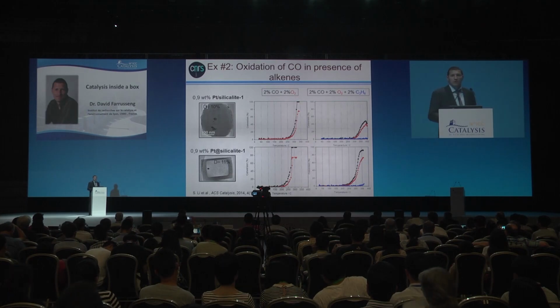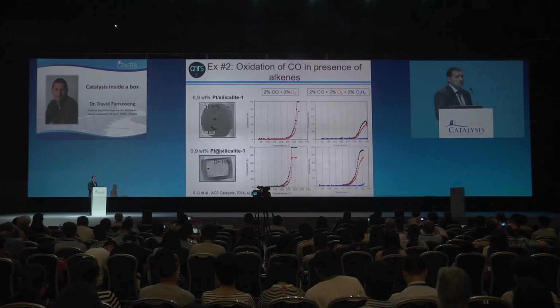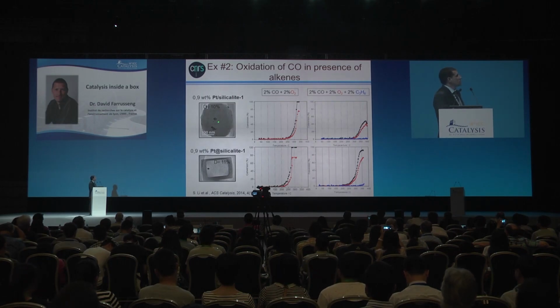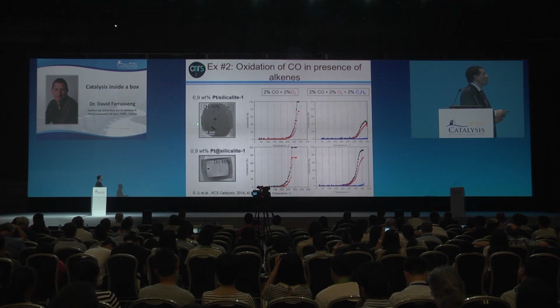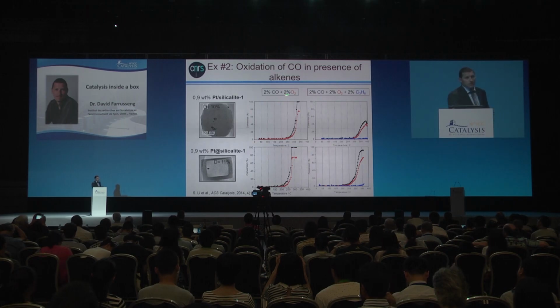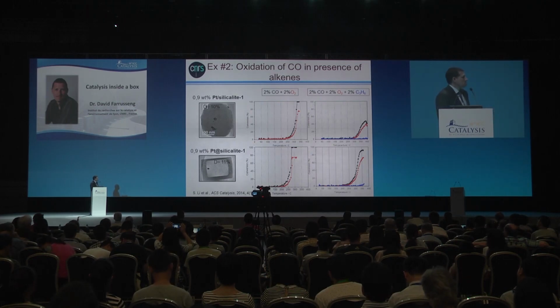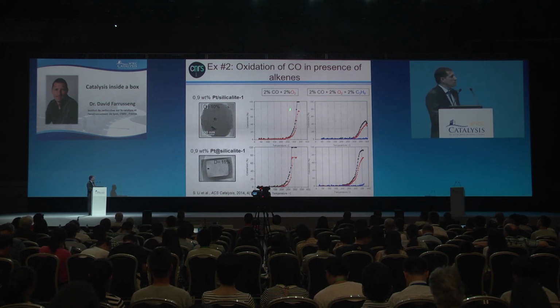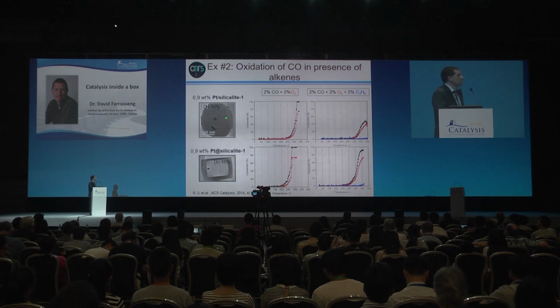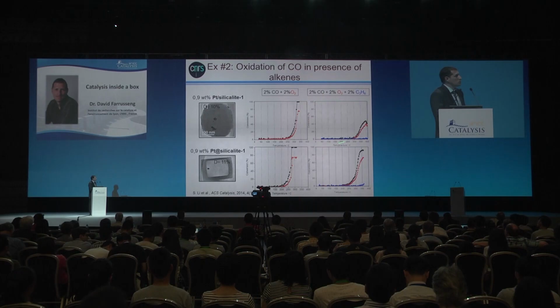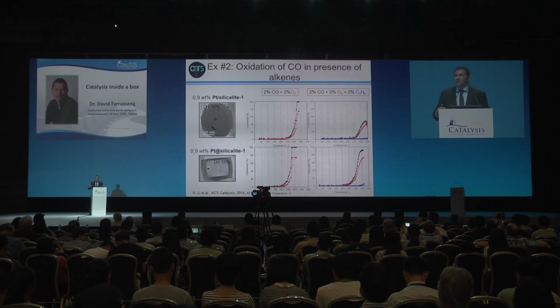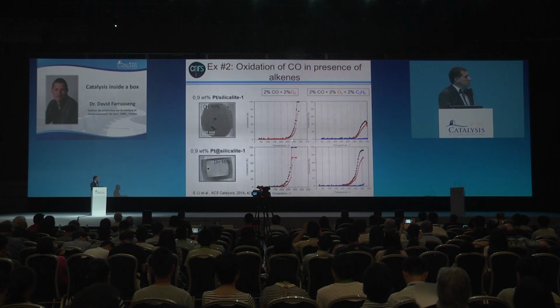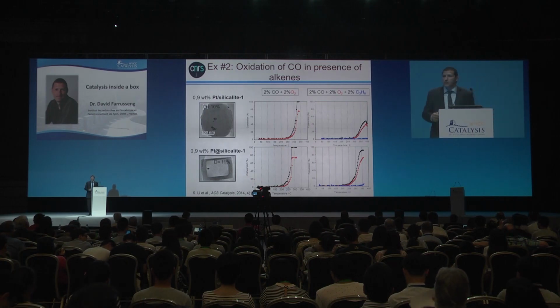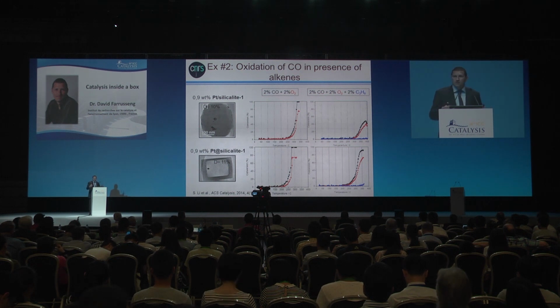And here is the comparison of our system with the conventional platinum in silicalite. The standard was just an impregnation of platinum solution on a silicalite 1. You have particles inside, you have particles also outside, and here is our material, so to say. You can see the CO oxidation is the very same for both. Again, in the classical catalyst, what you see when you introduce propylene is that the CO conversion levels off at 40%. Basically, the propylene poisons the surface of your catalyst. You can even see a shift of the light-off temperature from 250 to 300. This is the sign of surface poisoning by the propylene, because they have both the same activity regarding the metals.